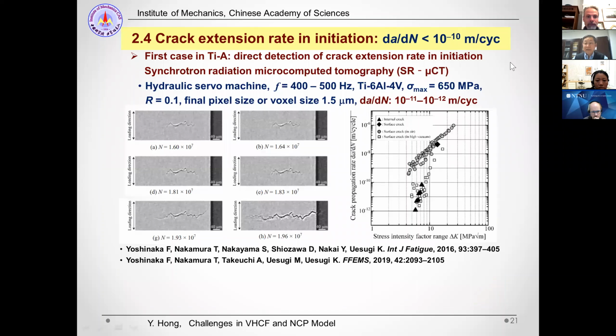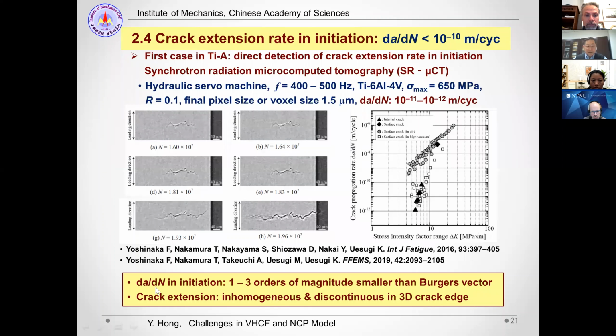Okay, so now there's another direct measurement of crack extension rates by a very new kind of method, synchrotron radiation micro-computed tomography. They can use this method to observe the crack growth and obtain crack growth rates between 10^-12 and 10^-11 meter per cycle. So we noted that the extension rate in initiation is 1 to 3 orders of magnitude smaller than the Burgers vector, and this can be explained by the crack extension being inhomogeneous and discontinuous in the 3D crack front.